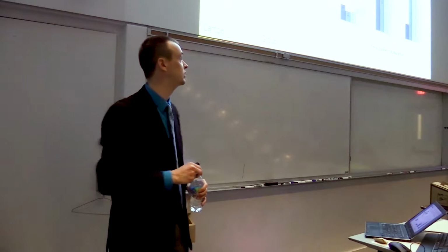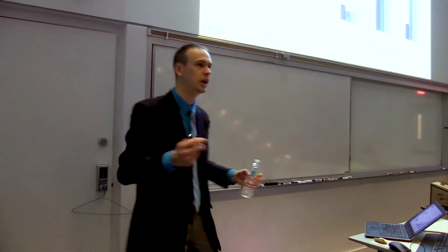And the more of it you have in the reduced form, so it hasn't eaten up a bunch of radicals first, the happier and healthier we think of these cells being. And so we see more glutathione in the reduced state in these hydrogels that are more degradable, these 100% degradable hydrogels. And that's true, again, right away, as well as after a week in culture, right? So these particular types of hydrogels have cells that have fewer free radicals and higher levels of glutathione.